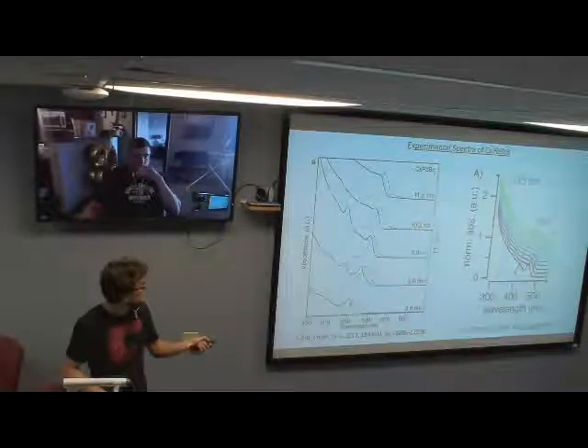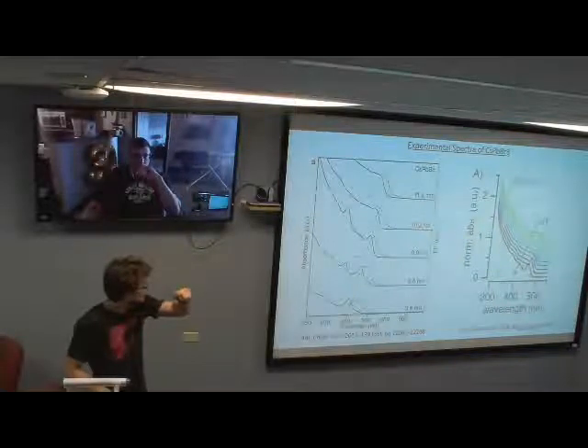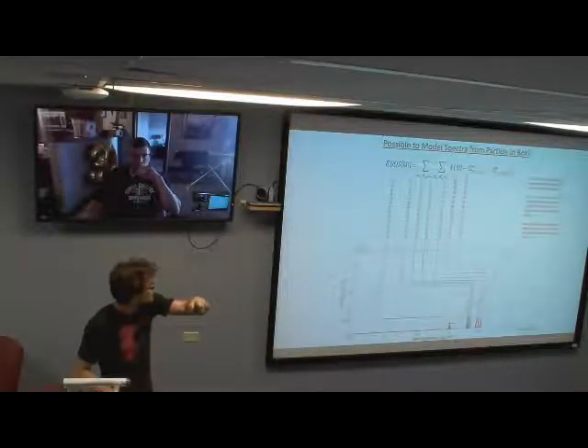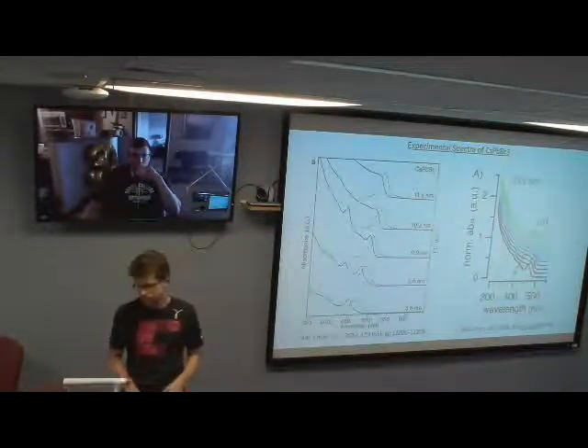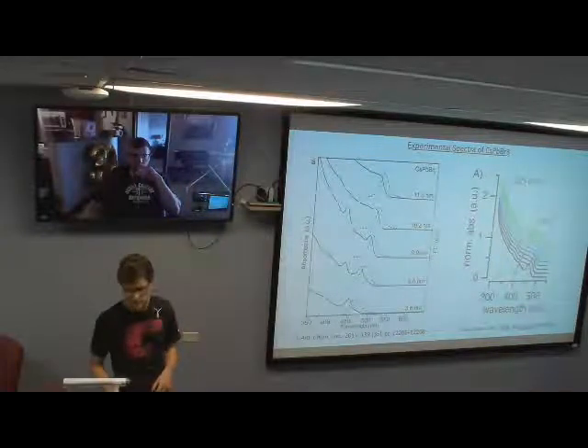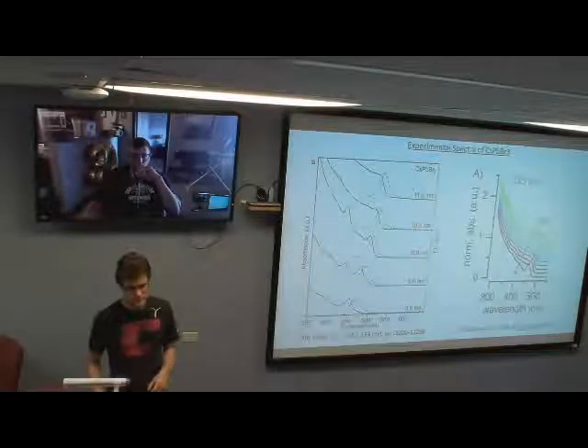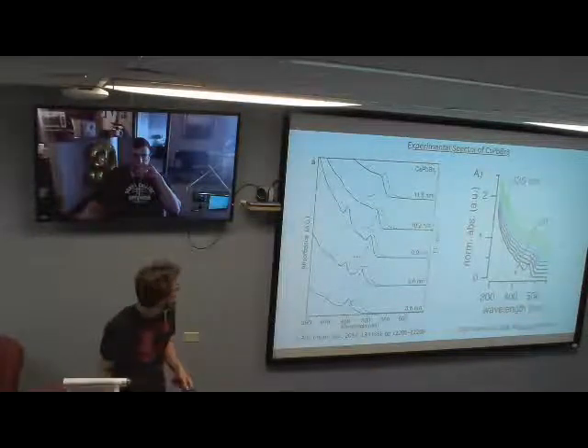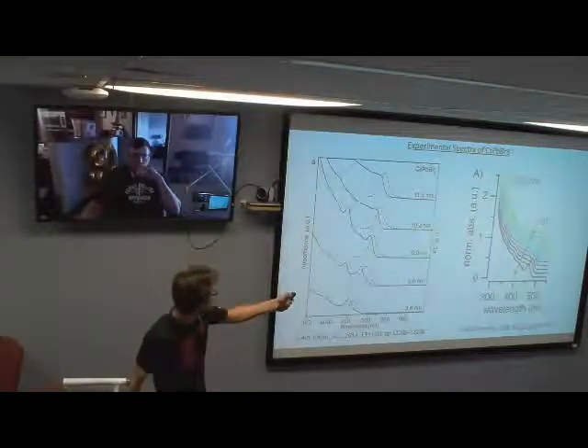So what is the exciton Bohr radius size for these materials? This is a parameter people use to say where you really should have the confinement effect being significant, where you really can see this splitting in levels. For this one it's 7-8 nanometers, and you kind of see it here, so 11, 10, 9, it shifts a little bit.